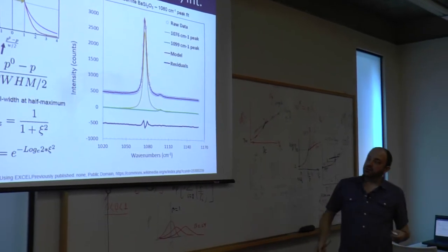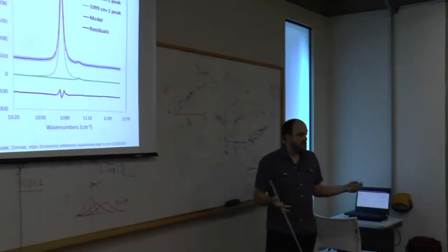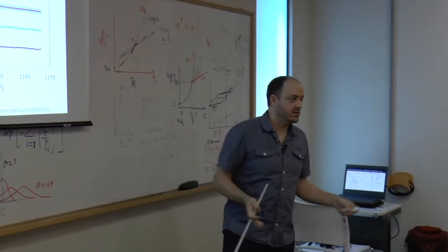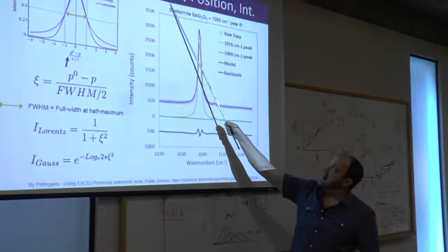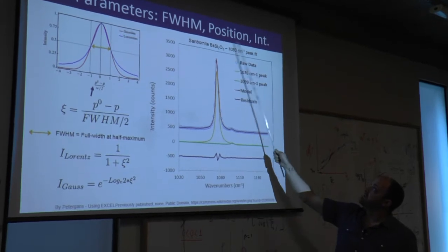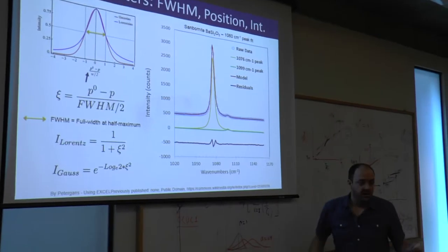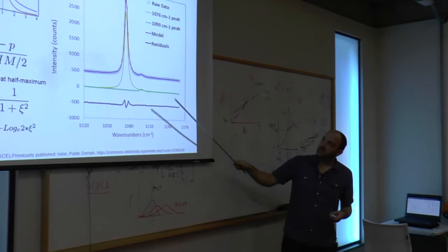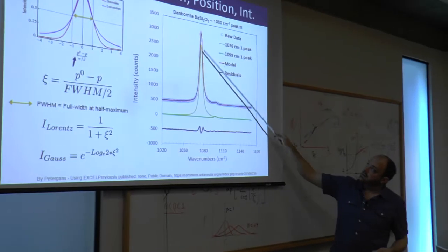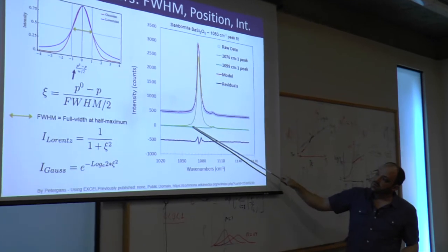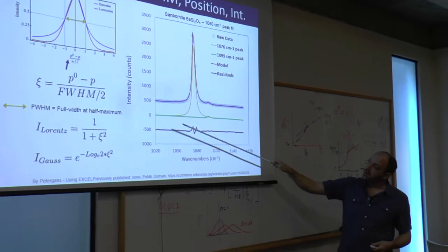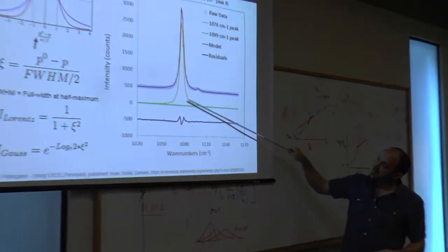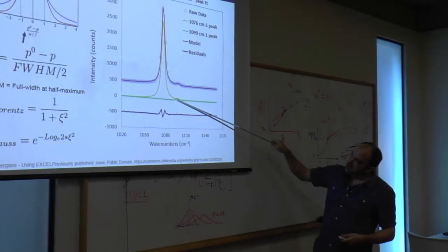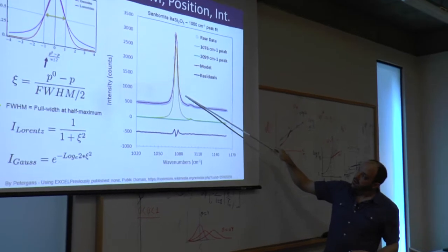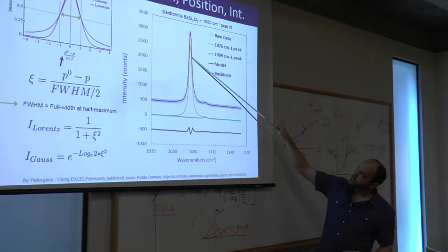So there's three main parameters for any peak, whether you're using a Gaussian distribution or a Lorentzian distribution or some sort of other distribution for the line. And that is the full width at half maximum, its position or its center, and the intensity of the peak. Of course, we only care about relative intensities. For our example, our original peak here in the mineral sanbornite, I fit the main peak with one Lorentzian curve here in yellow. And there's also a little tiny bump here, which I've had to put in another peak to fit. The circles here are my actual data points.